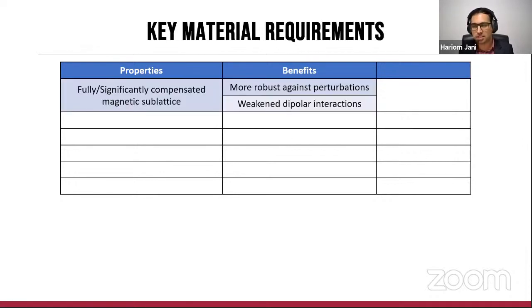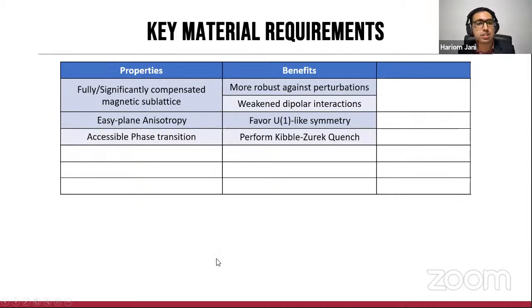So first and foremost, we want the system to be antiferromagnetic, or made up of significantly compensated sublattices, which would allow us to make the system robust and weaken dipolar interactions. It should have an easy plane anisotropy, which would favor U(1)-like symmetry. This is one of the conditions. There could be other ways of realizing the symmetry as well, but we felt that this was something easier to achieve, for example, than in an axial system. It is then important to actually have access to a phase transition to then perform the Kibble-Zurek quench. It would be beneficial to have low Gilbert damping, so once we obtain topological textures, they can be driven at ultrafast speeds.